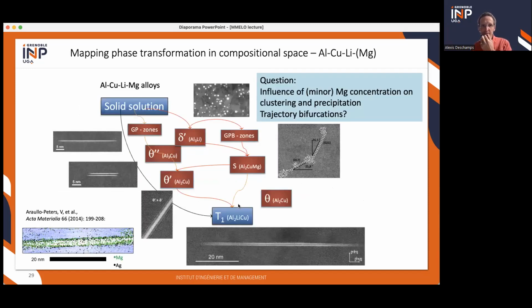The first case that I will show comes back to these aluminum, copper, lithium alloys that I was talking about just before. In these alloys, you have very complex precipitation trajectories with many different metastable phases that one can form in their interaction with each other. The most desirable phase that you want to obtain is T1, Al2CuLi. But you can get many others, and this depends on temperature, deformation, and alloy composition. The question was, what is the influence of magnesium concentration, which does not take part as a major solute element within the precipitates you want to form, but still has an influence on the precipitation trajectory?